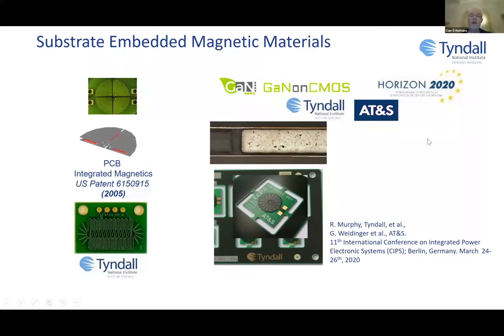So over the last 4 years, we got involved in a European project with an Austrian company who make printed circuit boards. And what they do is they actually embed silicon chips into their printed circuit boards. So what we wanted to do with them is see, could they embed magnetic materials into their printed circuit boards? And we have been working with them over the last 3 or 4 years in terms of doing that. So this would be a cheaper way of making magnetic components disappear. Now they're disappearing into the printed circuit board. There is a challenge here that the footprint of these particular inductors is going to be larger than what you can do on silicon. But there are applications where it can be used.